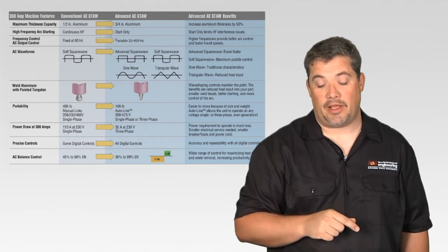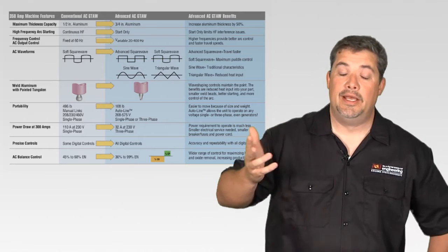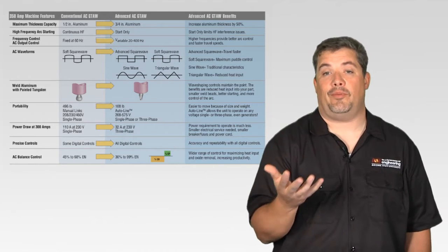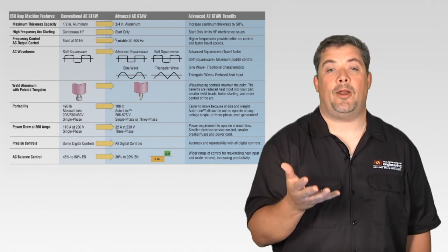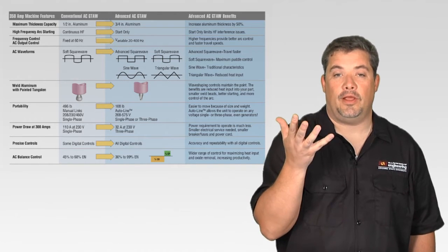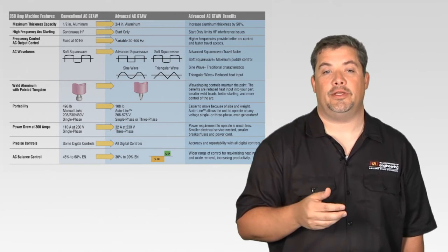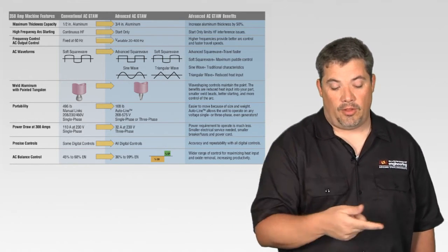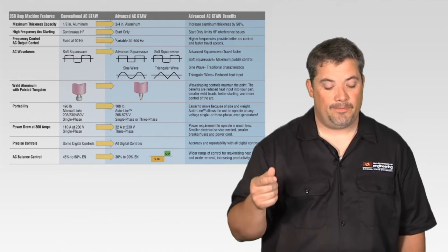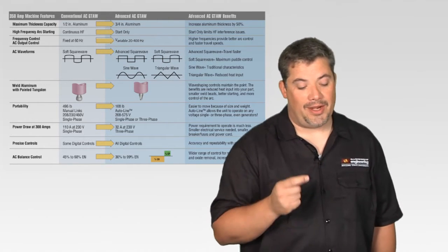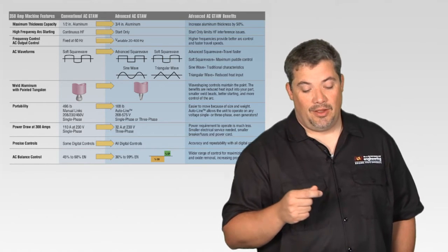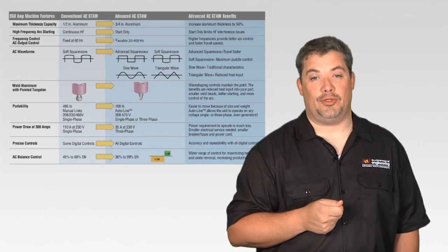The conventional machine had that soft square wave. Well, on the new machines, I've got all 4 wave shapes to pick from. Again, it's a heat energy thing. What works for my application? What gives me a better result so I make my weld as efficiently as possible. Instead of a ball on the tungsten, we use a point on the tungsten. Our portability goes from a 496-pound machine to a 108-pound machine.